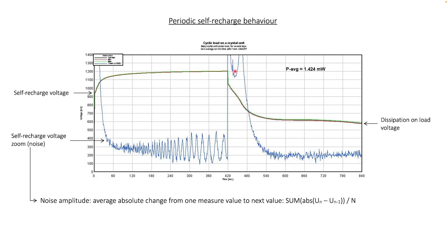Well, on the side where the crystal cell is loaded, we have first a drop of the noise level, then a very steep rise of the noise level before it comes down. And in this case, we have only a small oscillation here on the dissipation side of the diagram. On other days, we also had a higher oscillation here and a lower oscillation here on the other side, which again suggests that there are internal procedures in the crystal cell which take place and which change with time from one day to the other.